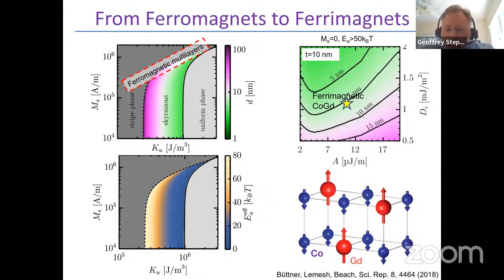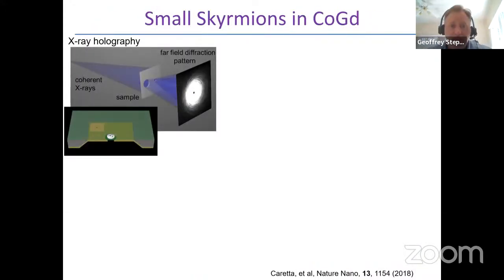With ferrimagnets, that can happen, particularly with rare earth transition metal ferrimagnets, because there is not only a reasonably large exchange interaction, but there's a bulk contribution to the magnetic anisotropy, such that in addition with the lack of stray fields, one can make these films relatively thick. And we had computed that for films on the order of several nanometers thick, with parameters of cobalt gadolinium, skyrmions with sizes of the order of 10 nanometers or less should be stable, and should be stable at room temperature. And so we went about demonstrating that experimentally by using X-ray holography, which is an X-ray technique that gives very fine spatial resolution, and it has elemental sensitivity